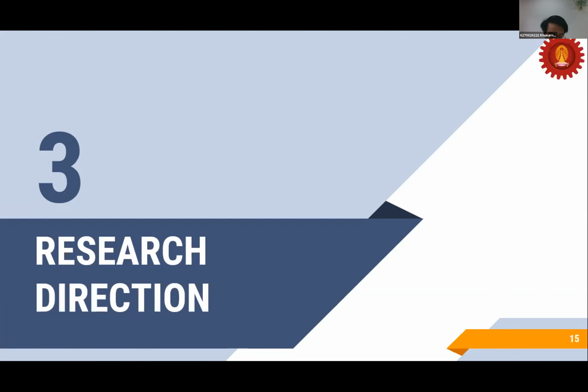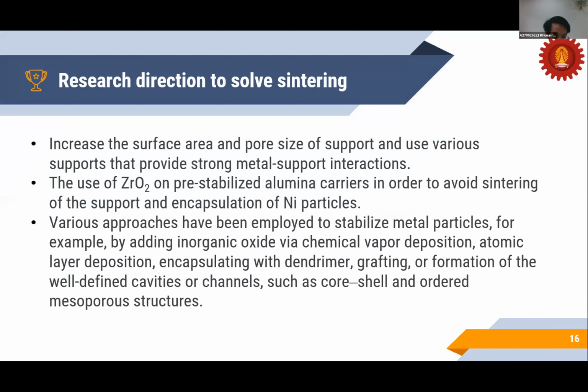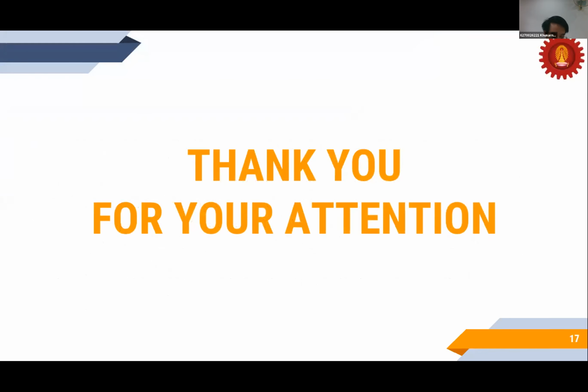Finally, the research direction to solve sintering. I suggest that firstly, increase the surface area and pore size of the support and use various supports that provide strong metal-support interaction. Secondly, use ZrO2 on a pre-stabilized alumina carrier to avoid sintering of the support and encapsulation of nickel particles. Finally, various approaches have been employed to stabilize metal particles. For example, by adding inorganic oxide, chemical vapor deposition, atomic layer deposition, encapsulating with dendrimer, grafting, or formation of a well-defined cavity or channel such as core-shell and other mesoporous structures. Thank you for your attention.